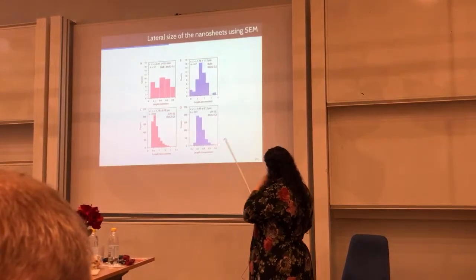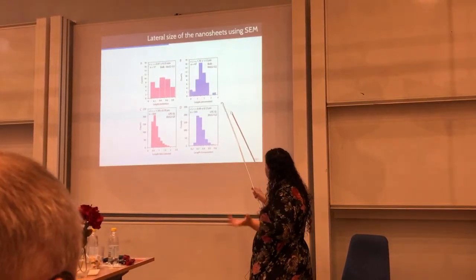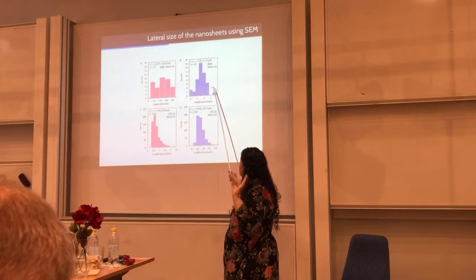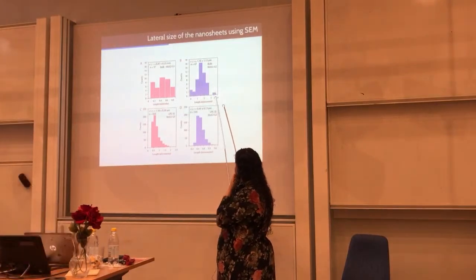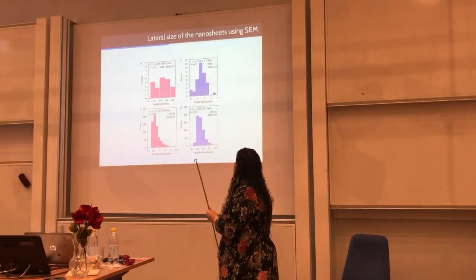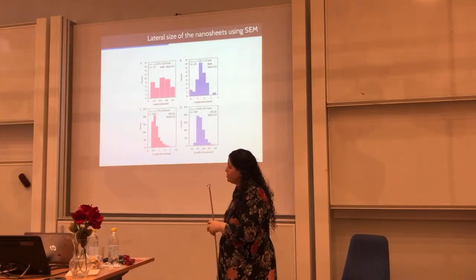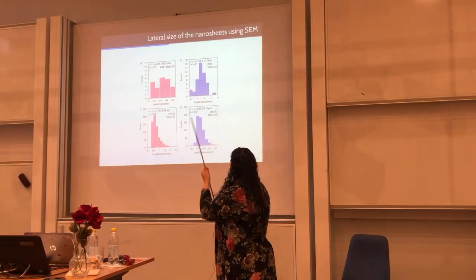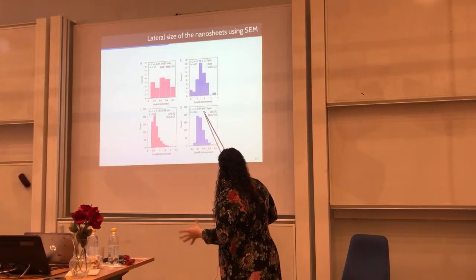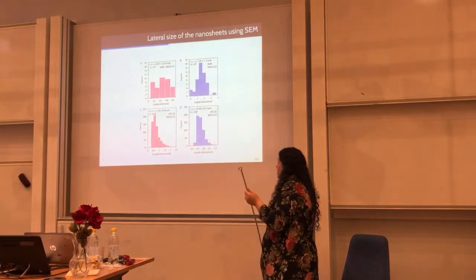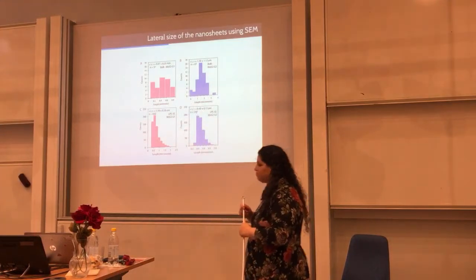Okay, so this other material is the same material I use in the other papers. It's this bulk molybdenum that has a much smaller particle size we start with. And after exfoliation, the particles were around 0.4 micrometer in size.